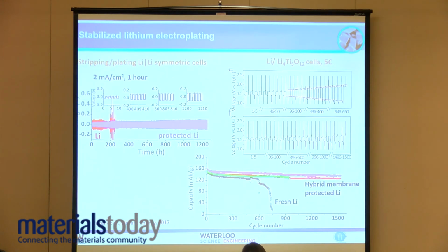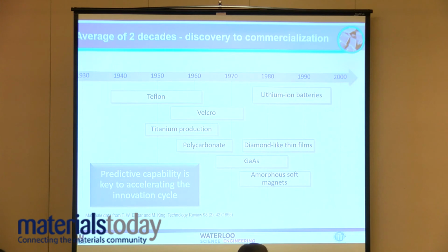And this allows us to stabilize cycling, in this case over 1,500 cycles, with a variety of these different alloy films with little increase in polarization over the duration of the cycling. But this is kind of for any electrochemists in the audience.